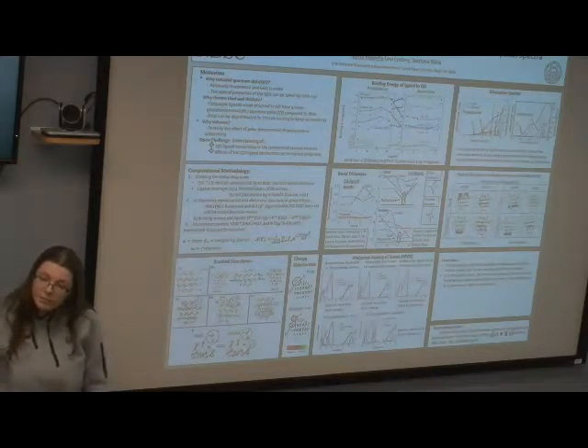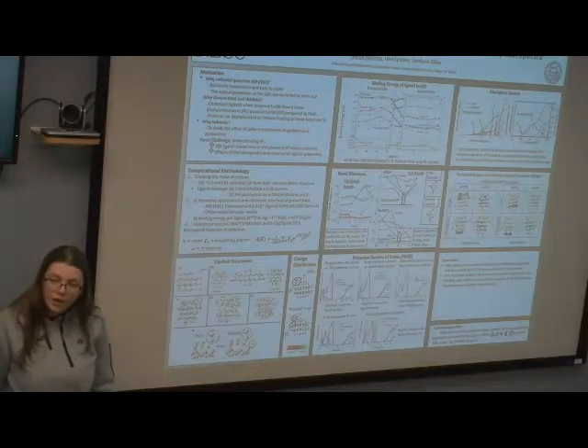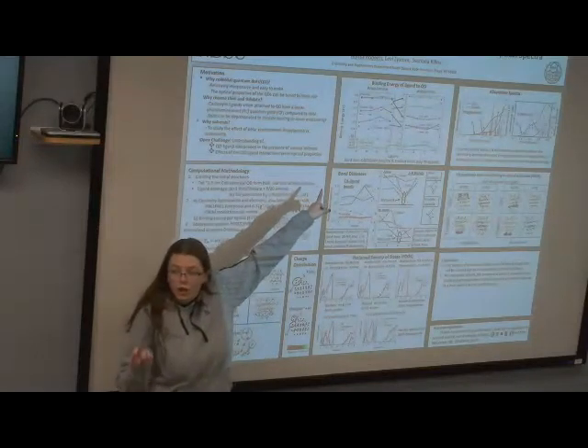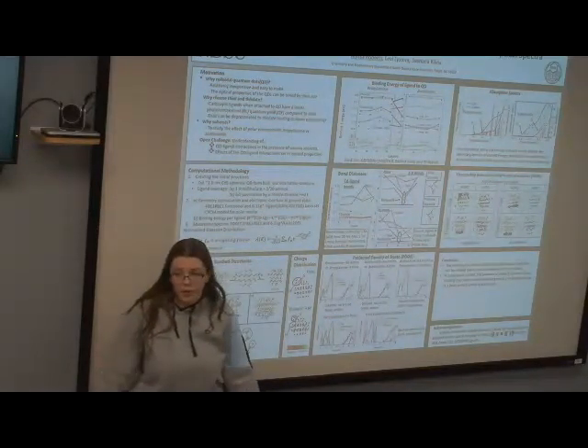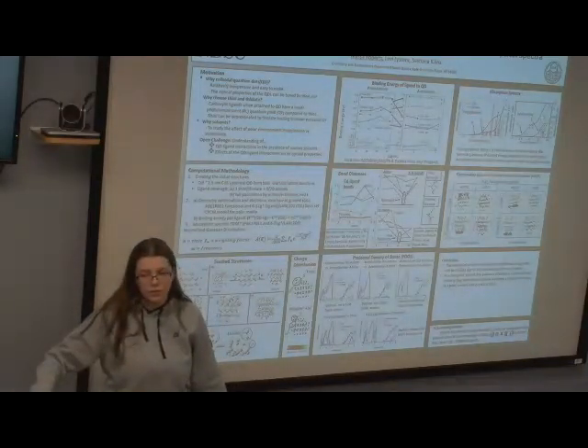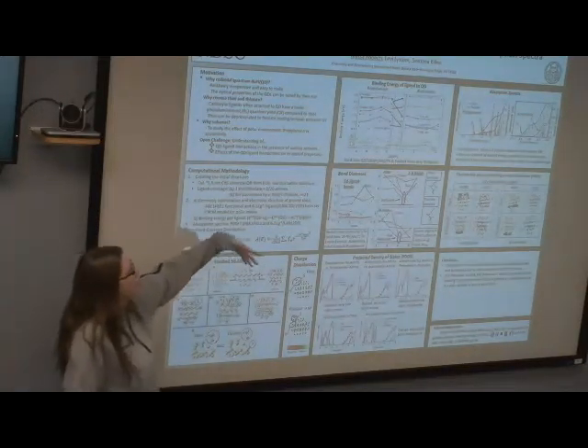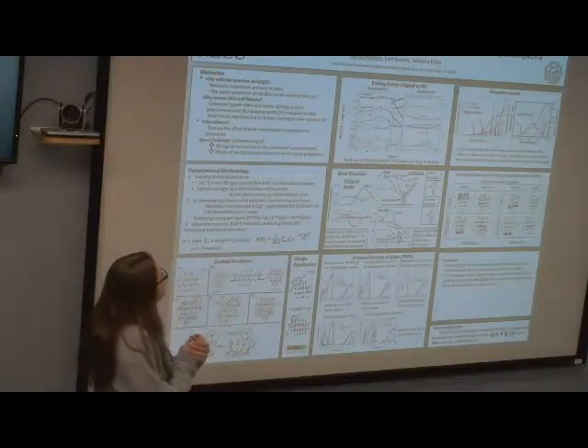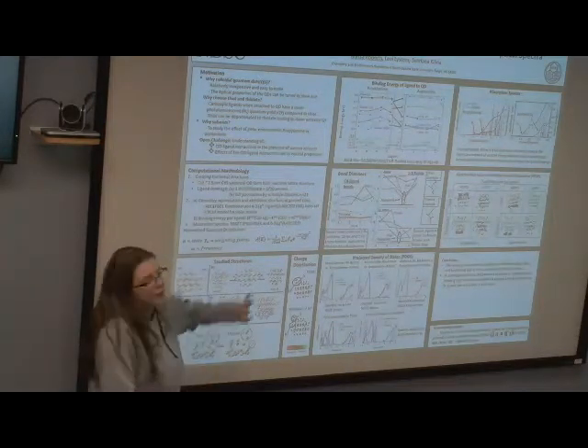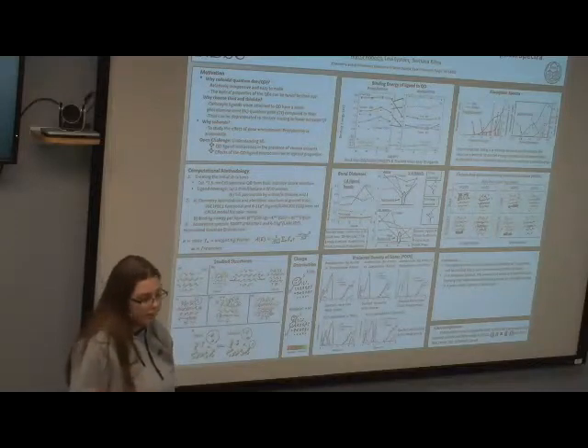Would it be correct to say that binding energy becomes stronger in polar solvent? No, other way around. So the more negative the binding energy, the stronger the bond is to the quantum dot. So this becomes less bound to the surface, if that makes sense. Mm-hmm. Okay. So basically a trend that you can see is that amine is necessary for acetonitrile, for thiol and thiolate, so that it kind of stays on the surface. Otherwise it could float off. I don't really know the technical term for that, but anyways.